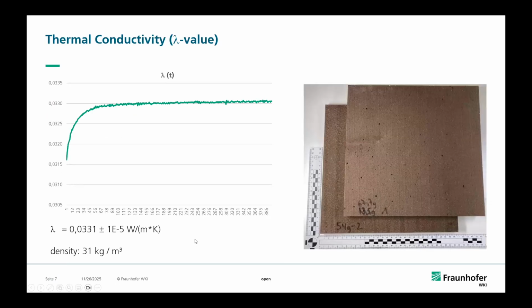Now, I give you two examples which we have done here in our lab. So we produced a foam and measured the thermal conductivity. This is for insulation materials, and you see the thermal conductivity in this example was 0.033 watt per meter per Kelvin. The density in this case was 31 kilogram per cubic meter. So that is quite good for a polyurethane foam. We can compare this with conventional petro-based foam. They're in a very similar range, actually.